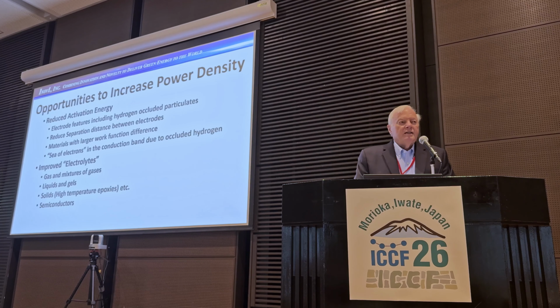Okay, this also points to what we can do to increase the power. Electrode features including hydrogen-filled particulates. In fact, multiple people have presented their powders, and so far, every powder that we have tested, if it produces heat, it will work. It has worked for this. Now we have a very limited number of those tests, and if that's something you can do, we could get some help from people here.